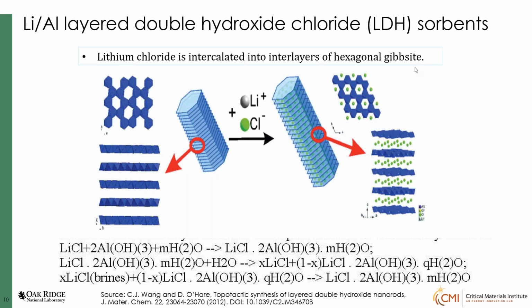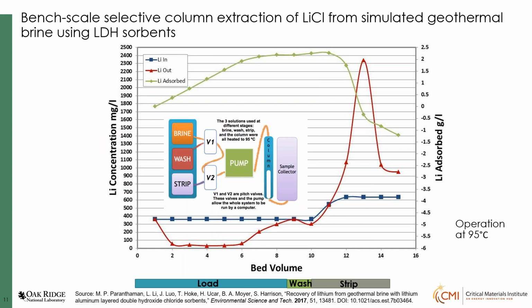Next slide, please. So we have done column extraction. This is a schematic of a column extraction where you have a geothermal brine and a wash and strip method. Here we are plotting lithium concentrations against bed volume for load, wash versus strip. You can see the lithium is adsorbed, and the concentration is about 300 to 400 ppm of lithium here. We can get mostly the lithium out in a bed volume.